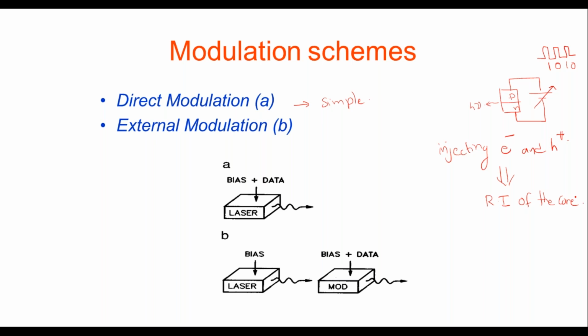The laser diode, please remember, is supposed to emit only at one particular wavelength. It should always be emitting at lambda naught. But because of this injected carrier density, there's a change in the refractive index of the laser cavity, because of which this lambda naught would slightly deviate. There is a slight drift in this lambda naught. This would become either lambda naught plus or minus delta lambda. There's a change in the wavelength at which the laser diode operates.